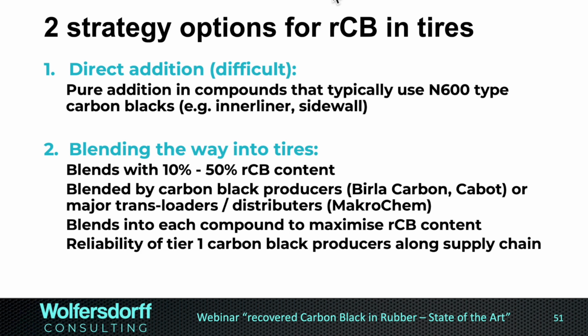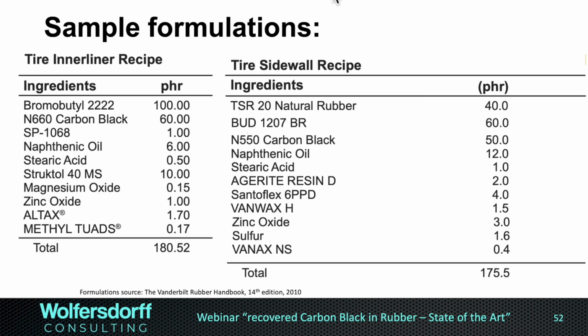So with a blend, really, we can go in every compound and put a small part of recovered carbon black with a defined performance, which is guaranteed by the reliability of the tier 1 producer, and they control everything along the supply chain. So tire makers, when the carbon black makers resell blends or resell recovered carbon black, they have, of course, more reliability than the recovered carbon black producers, mostly small companies themselves. So let's look at some sample formulations.